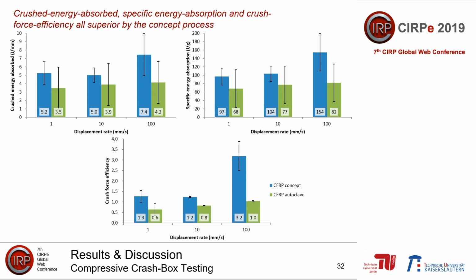And then in blue we have parts produced in our concept process. In green we have parts produced in the autoclave. And we can see the first observation is that parts produced in our process exhibit superior properties to the autoclave. The second observation is that generally as we increase the displacement rate, each property increases. Now these observations can be explained by the deformation behavior.